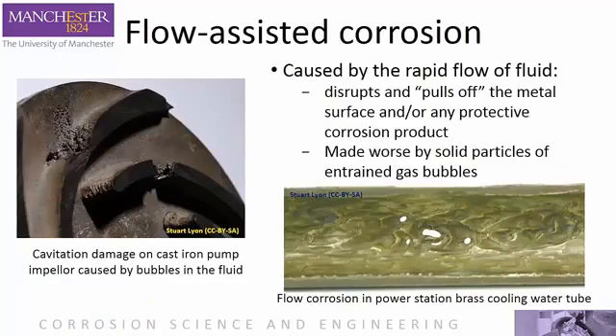Flow corrosion or erosion corrosion can be caused by a number of processes, including cavitation, which is more of a mechanical effect where gas bubbles entrained in a fluid implode as they move from a low pressure region to a high pressure region and cause damage, commonly in pumps as shown in the image here. The other main type is called flow-assisted corrosion, where the rapid flow of the fluid literally pulls away the top protective layers of the metal. In this example, flow corrosion in a power station cooling water tube has caused severe damage and ultimately leaking.